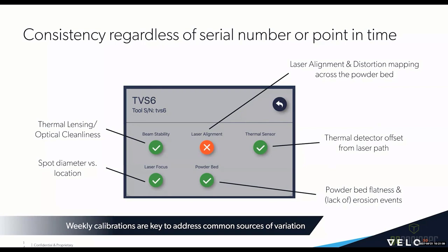And then also we're able to look for erosion events. Erosion events can occur if there's a problem with the gas flow, where it's basically eroding away the powder bed. So we verify for that as well. So all these calibrations together, these are done weekly by a technician, as I was saying, and we find them key to ensuring that there's not variations in the build across Sapphires.